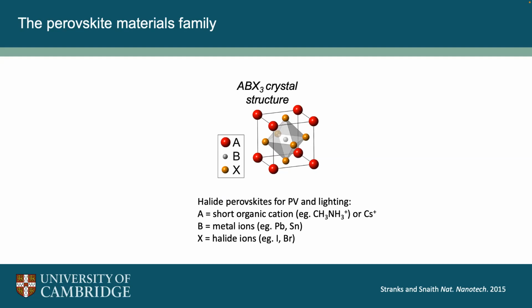But the materials we're working on for PV applications and other applications are halide perovskites, and they typically have in the A site an organic cation, so methylammonium, or an inorganic cation, cesium, so they're typically small cations. In the B site, there's typically a metal, so lead or tin. There are some other metals being used as well, and the X site is a halide. These are essentially human-made minerals. They're not found naturally occurring. We make them in the lab, and they're very different from the minerals that we find in the Earth's crust, other than sharing the same crystal structure.